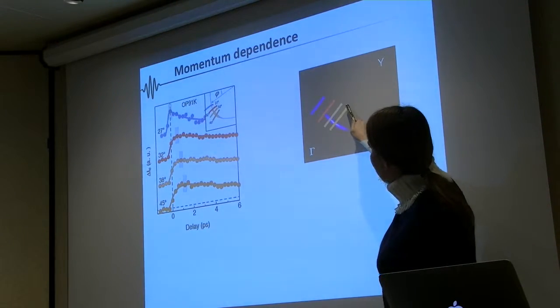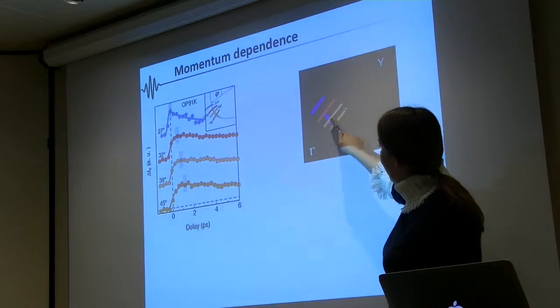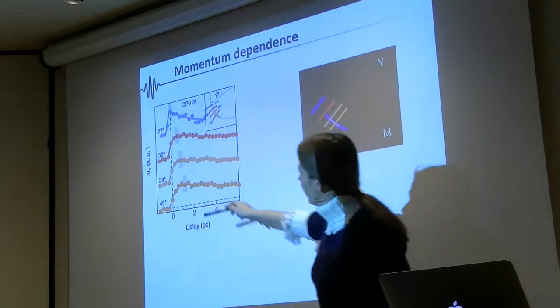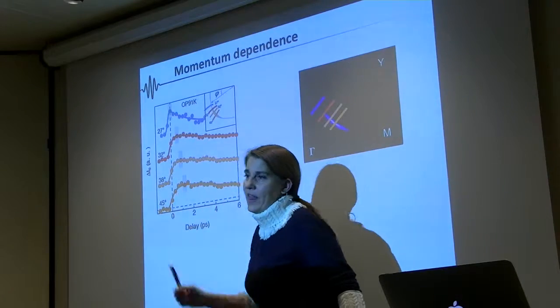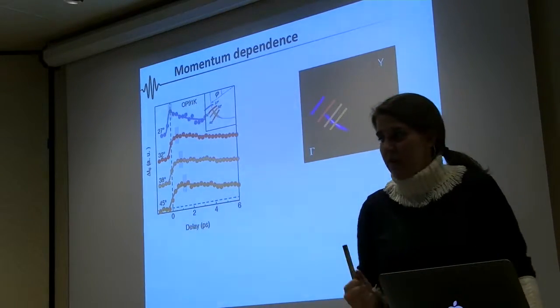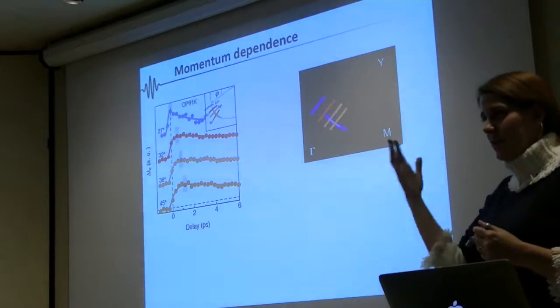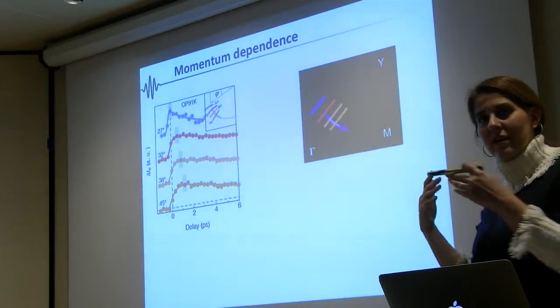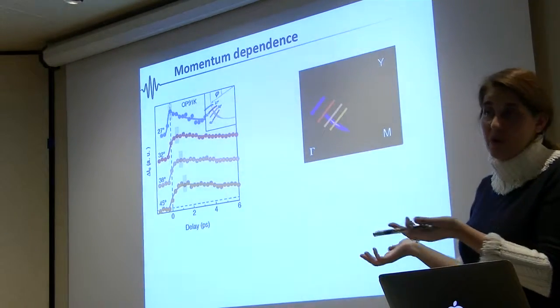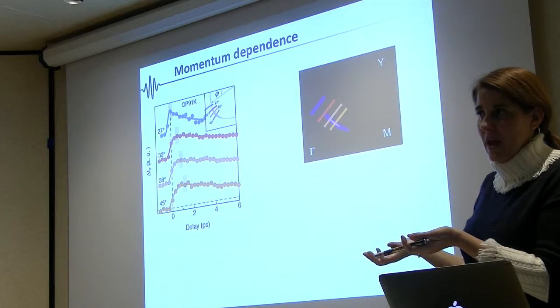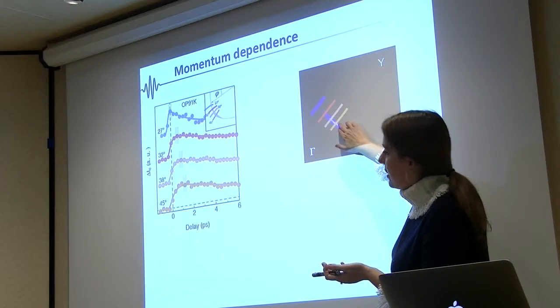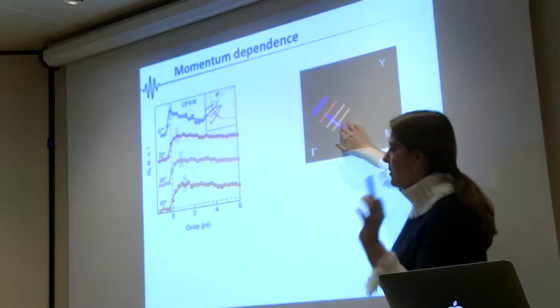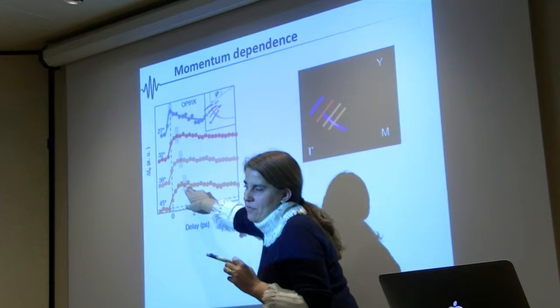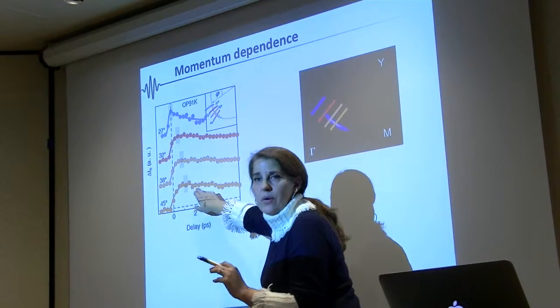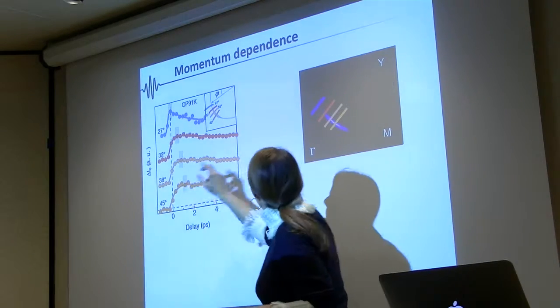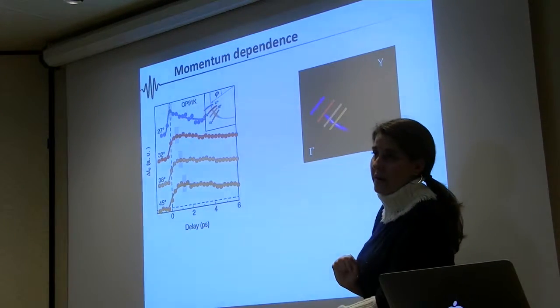So you see that if I'm here at the node, away from the node, all the way up to this point, there is always a delay in the response. So far I led you to think that this delay is related to the superconducting gap, which actually is. So you come in, the system responds, it takes some time before responding. Every single thing we looked at takes time to respond. This is true as I move on the Fermi arc.